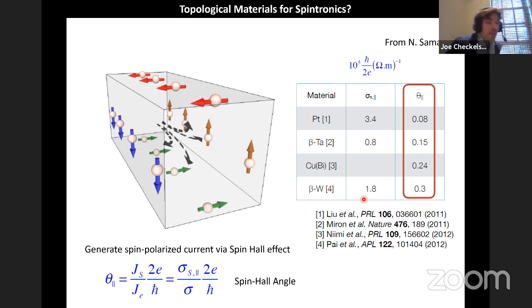So just in a minute, let me try to describe to you, and I hope you could follow a lot of these references. Something that's very important in the field of spintronics is the ability to use some heavy element materials to deposit spin angular momentum into other materials. And there was a revolution recently where they realized systems which have a so-called large spin Hall effect, systems where when you have a spin current, the two opposite spins will move in different directions, perpendicular to the direction of motion, that you could use this motion from the spin Hall effect to deposit spin angular momentum into, say, a ferromagnetic layer that was sitting atop this material.